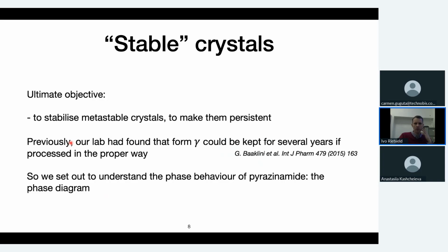Well, we came across the fact that the gamma form is the high temperature form. And if you make gamma crystals, which are metastable at room temperature, they could therefore give, say, a higher solubility, if you would like, for pharmaceutical applications. Normally, if you make gamma crystals, they convert into alpha crystals relatively quickly. Over a few days, generally, everything would have turned into alpha crystal.